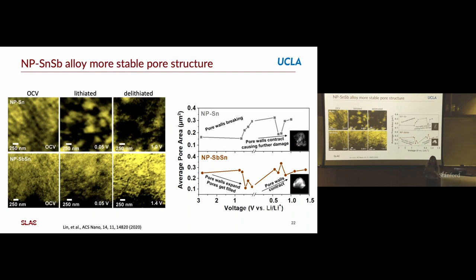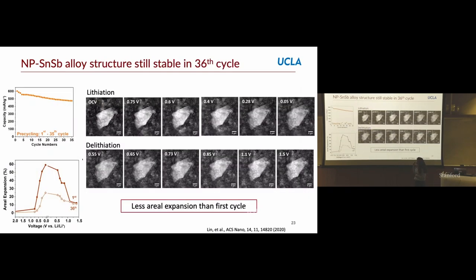So we think it's due to the fact that we have this dual alloy. We have this tin and antimony, which can lithiate at different voltages. You can also plot the average pores and see that graphically as well.